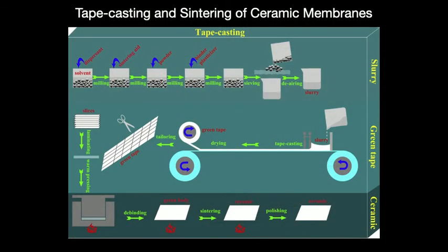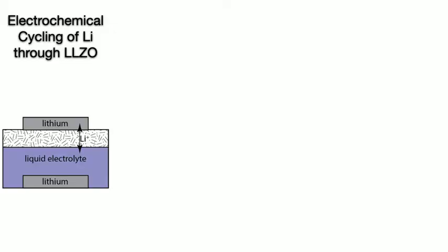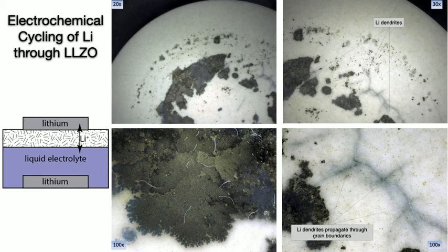The problem is this is not a simple process. It's an expensive process. It involves tape casting of a slurry to make a green tape. Those green tapes are typically laminated to form a laminate structure, and then that has to go through sintering. And as I say, you not only want to close all the pinholes, but you want this to be flat. There are other issues too. In work done at PolyPlus and by others on cycling of lithium metal through garnet, you can in fact see lithium dendrites penetrating this dense solid electrolyte through and along the grain boundaries.